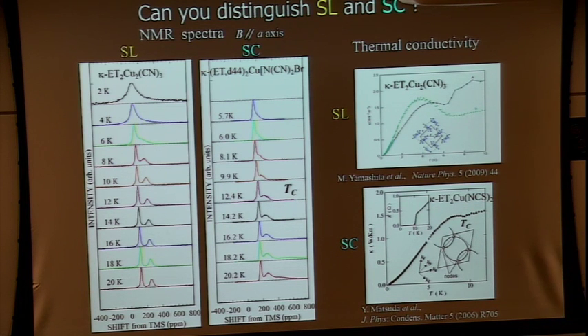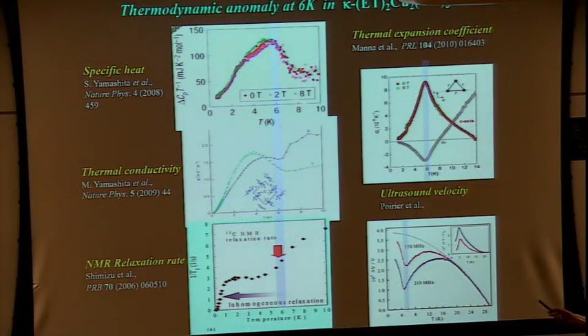However, yeah. This can be some origin of the spinon Fermi surface, but I don't know. I'm not sure, because the temperature is rather lower, 6 Kelvin. This is the delta C divided by temperature. So the whole specific heat is very huge, and then the lattice part is subtracted, and such a broad shoulder results. But in this sense, this shape and the anomaly associated with the superconducting transition look similar, yeah. But we cannot compare in detail the two behaviors.